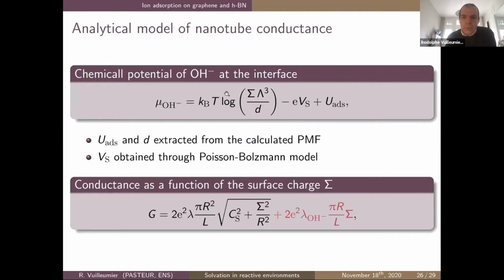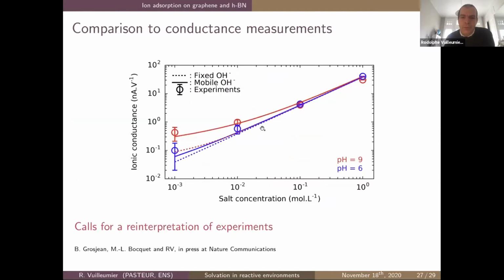So we need to use other techniques, and we've simply used theoretical models describing a Poisson-Boltzmann description of the potential at the surface, and then the chemical potential on the surface depends on the Poisson-Boltzmann induced electrostatic potential at the surface. And we've also used a model for the conductance as a function of the surface charge, to which, however, with respect to the typical model, we've added this extra ingredient that the charge is not fixed on the surface, but can diffuse and can give a surface conductivity at the surface. And in particular, this second term is very important to reproduce experiments.